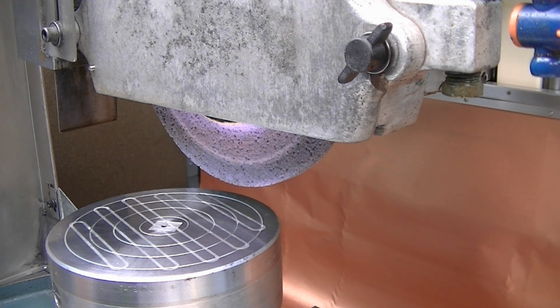And with normal grinding, slowing the actual traverse rate of the path across the part, in this case working radially out off the part, when you slow that way down, you can get greatly improved finishes. But it also increases that thermal time for it to grow up as it's doing that, changing the shape of the part. Now these parts are going to get lapped where it's important anyhow, so it's not critical that they're perfectly flat as ground, but the closer they are, the easier it's going to be to lap. And it's always fun to just practice on getting good geometry as ground.